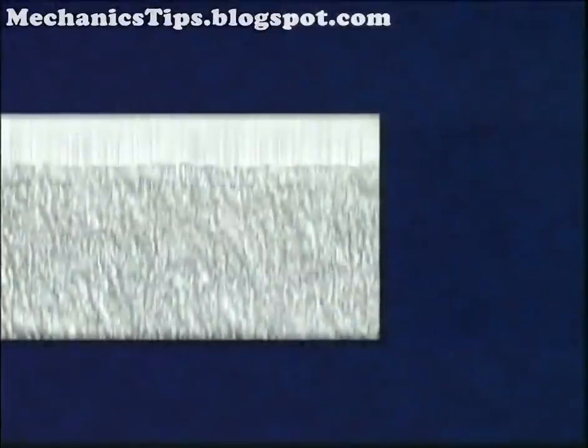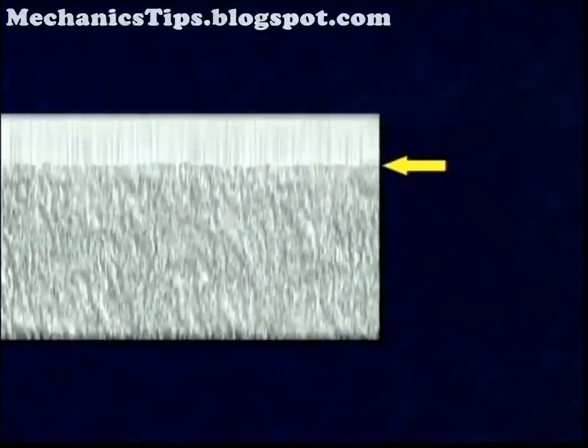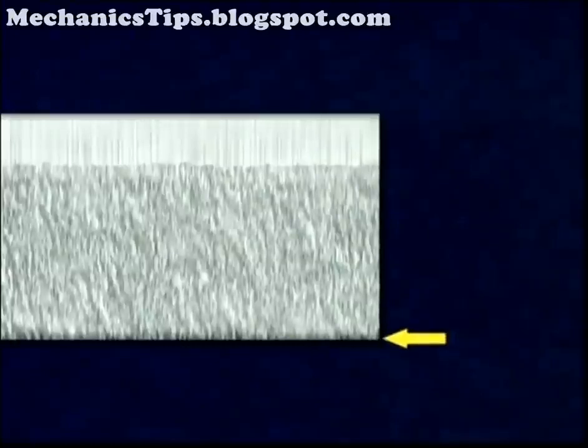The shear blades typically penetrate the stock no more than 1/3 of the stock thickness before the slip plane occurs. The exact amount of penetration varies with material hardness and knife clearance.